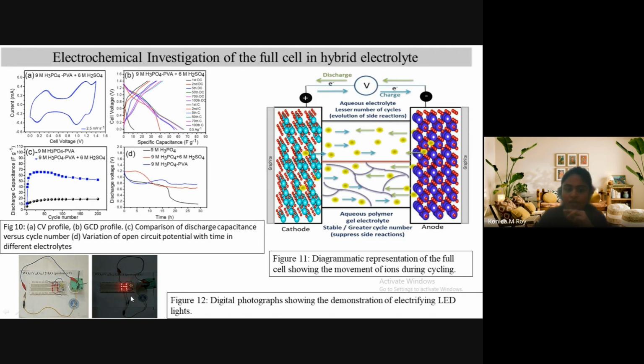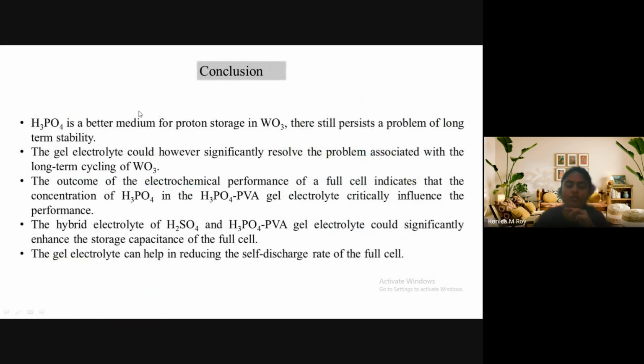So here is an application of lighting of this combination, and it could light up for 5 minutes using this electrolyte. So in conclusion, we could see that H3PO4 is one of the best electrolytes for proton storage in WO3 at higher current density. The gel electrolyte could resolve the problem of long cycle life. Apart from that, the hybrid electrolyte could increase the storage capacity, and with the concentration the performance was getting better, and the gel electrolyte reduces the self discharge of the full cell.